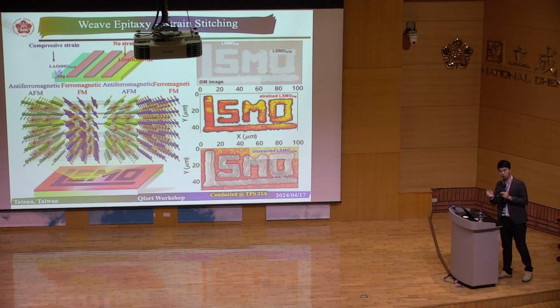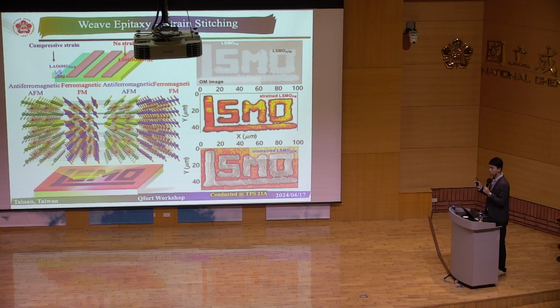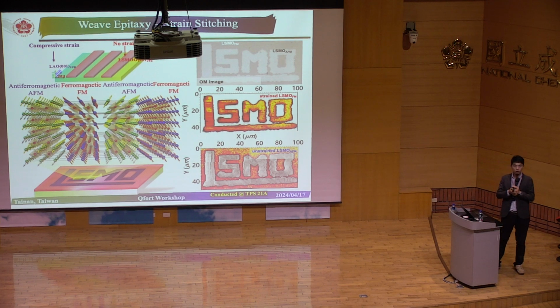We can use some spatial techniques, for example nano-diffraction, X-ray nano-diffraction, to reveal the strain structure. It tells us that the places that are orange are the strained LSMO. And if you look at the outside area, it suggests where the unstrained LSMO is. So if you are convinced by the phase diagram and by the X-ray diffraction, I hope you are convinced that we can essentially control the magnetization state. But this is not real evidence.